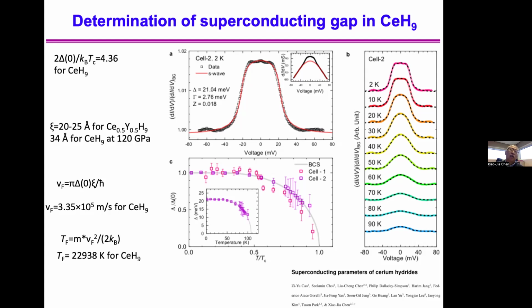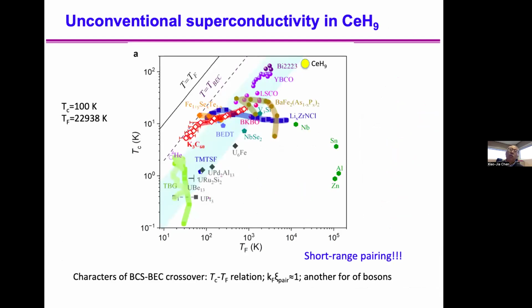From that, we can determine the Fermi velocity. The Fermi velocity for CeH9 is 3.35 times 10^5 meter per second. That's why we can determine the Fermi temperature for this material as well. When we put it in here, you will feel it's really surprising, because you can see TF is pretty high. It's sitting close to bismuth 2223. It's close to the BEC line. It's a short-range pair. That's an unconventional feature for superconductivity in hydrides.